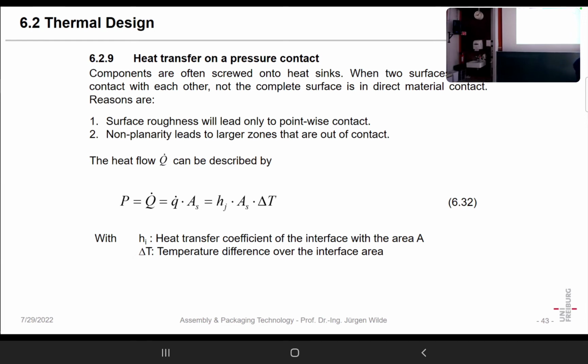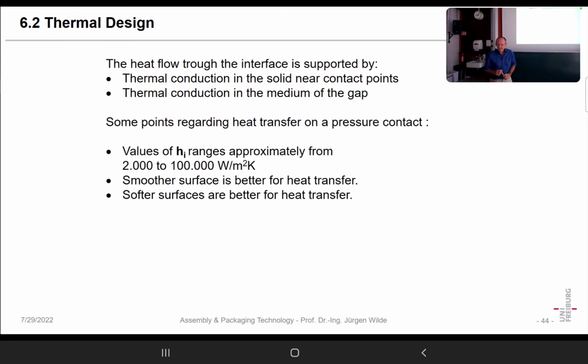If you have your kitchen stove and you have a pot and you have it just starting to boil, you can hear it. And when you press the pot, you can notice immediately the boiling sound will be stronger. It's interesting. And the reason is you have immediately more heat transferred. The more you press, the higher the heat transfer coefficient will be, because the area you press together is larger. Again, here we have that heat transfer coefficient. It is depending on the surfaces you have and on their quality. It is somewhere between 2000, which is really bad, and up to 100,000. So my idea is if you take such a value and you assume something, maybe you take 10,000 or so as a reasonable value.